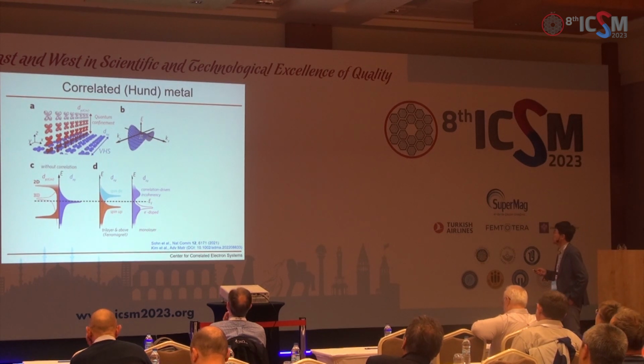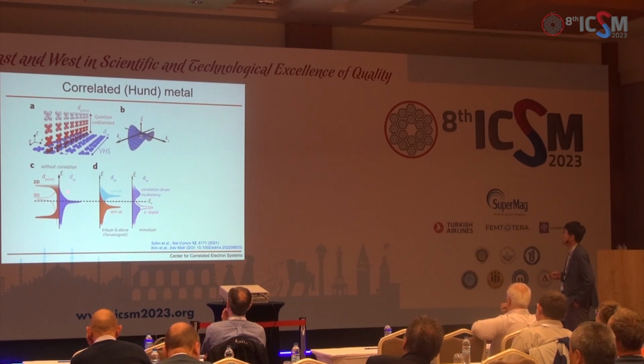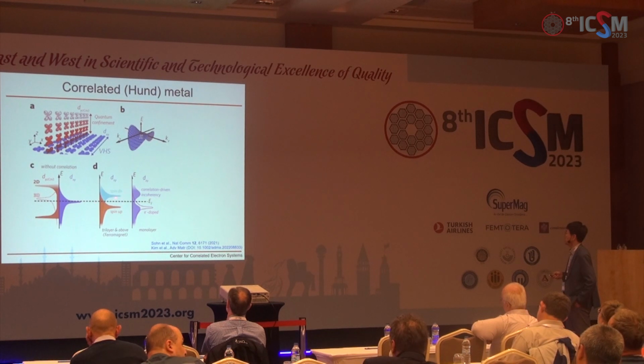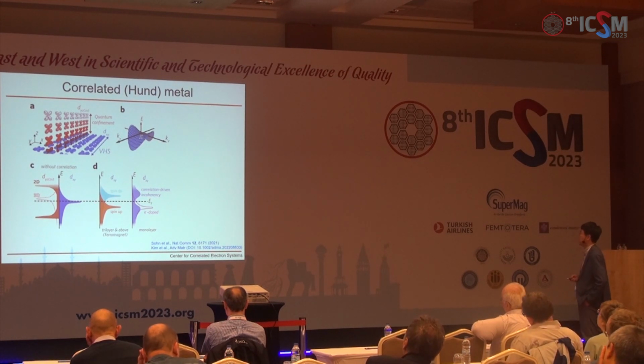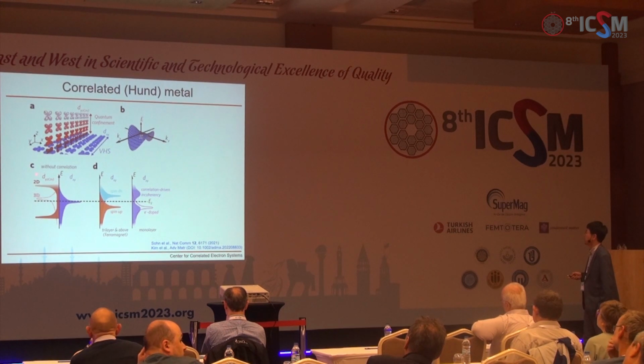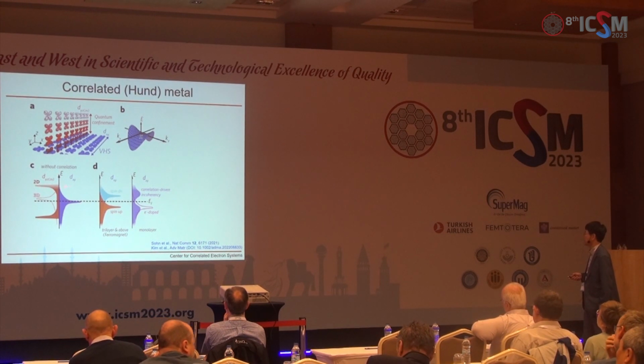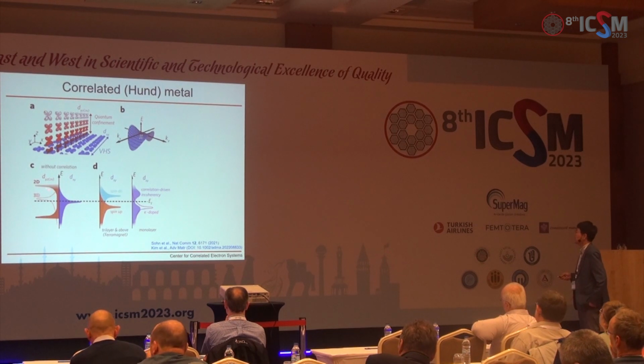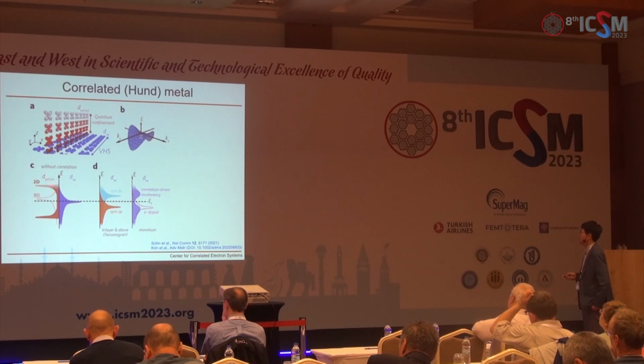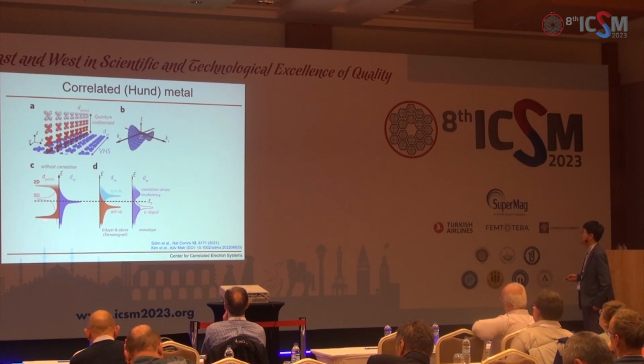This is very intrinsic. That's the main message here. So our picture is that when we go to a very thin film, a two-dimensional system, in 3-dimension, the structure looks like a 113, 3D system. We have spectral weight near Fermi energy, and that splits into spin up and spin down, resulting in a ferromagnet. On the other hand, in the case of 2-dimension, like 1 unit cell strontium ruthenate, due to quantum confinement effect, dxy and dyz/dzx orbital states have different density of states. dxy has a van Hove singularity near Fermi energy here. Meanwhile, for dyz/dzx, their density of states looks like this.